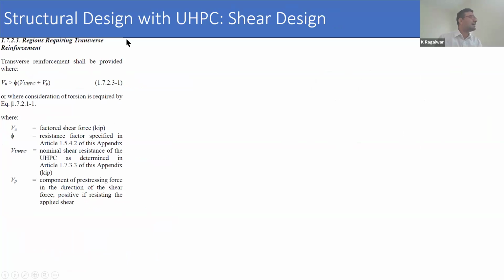The structural design with UHPC for shear is very straightforward, and I'm going to cover it in just one slide, very briefly. So what is different here? If we go back to our first slide, we saw that we had no large aggregates, and concrete shear strength comes from the interlocking of the aggregates. So there is no interlocking here. But instead, we have discontinuous fibers, which give tension-carrying capacity to UHPC. So they have come up with a modified compression field theory and used it to calculate the requirement of transverse reinforcement.